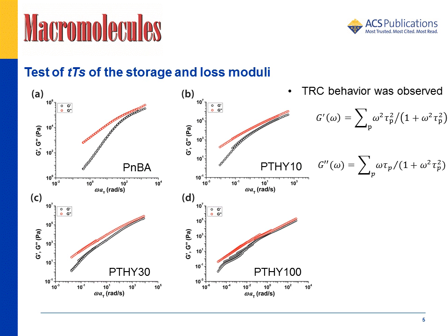Therefore, we managed to apply time-temperature superposition to compare our results to the theory. However, a thermorheologically complex behavior was observed. In order to overcome this issue, a pseudo-master curve construction was proposed using the G' data, since according to the Maxwell equation, the G' data are more sensitive to the sticker dissociation or slower modes of relaxation.